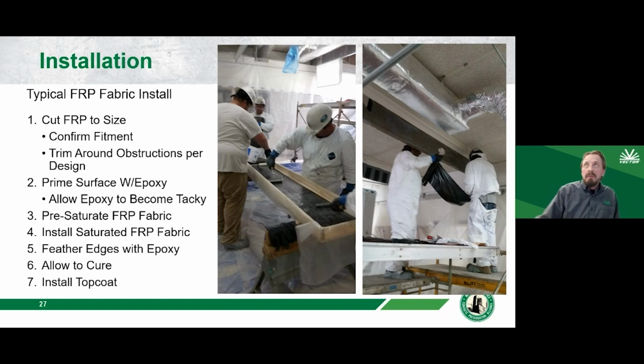So on this project, we had flexural strengthening. You can see the fellows on the right putting up a flexural piece, and then there are some stirrups, some U-wraps around the bottom of the beam. So put the big pieces up, and then our offcuts will be cut up into the smaller pieces as they're required. Do the surface prep. We'll saturate the surface of the concrete with an epoxy resin. Let it become tacky. Then we'll saturate the fabric itself. You can see the technicians there rolling the fabric and trying to put the saturant into the fabric.